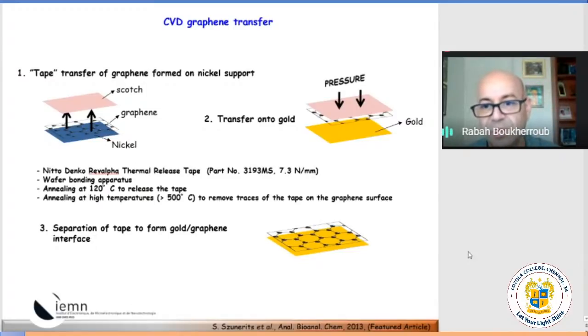Then I take this graphene transferred on the tape, and I can actually print it on different materials. It could be glass, it could be any substrate. So this is a very nice technique because you control really the number of layers. You can even transfer a single layer graphene to any substrate. However, then you have to release this Scotch tape. Otherwise, you end up with the substrate, graphene, and Scotch tape. Of course, you can do nothing with the Scotch tape. It's a polymer material. It's very thick. So you have to remove that.